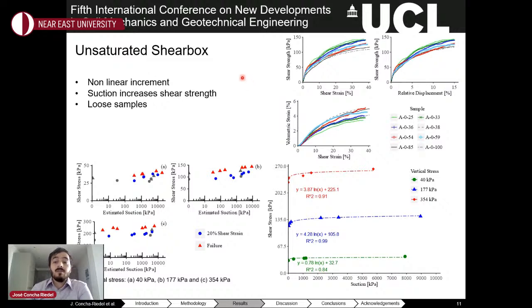The shearbox test results can be seen in the following plots. In the bottom left plot, the peak and 20% shear strength is plotted versus the suction estimated from the soil water characteristic curve. It can be seen that for all normal stresses, shear strength increases with the estimated suction. Points plotted in gray are samples that had higher initial voids ratio than 1.28. On the bottom right plot, peak shear strength is plotted versus estimated suction in a linear scale, which shows that the relationship between the two variables is nonlinear.